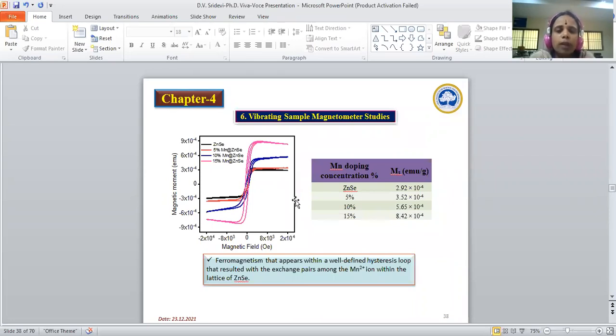This slide shows the vibrating sample magnetometer. Pure zinc selenide nanoparticles show weak ferromagnetic behavior, and the saturation magnetization value was found to be 2.92 into 10 power of -4 when the manganese ion is incorporated into the zinc selenide nanoparticles. The MS loops increase, so the saturation magnetization values increase. As a result, ferromagnetism appears with a well-defined hysteresis loop, resulting from the exchange pairs among the Mn2+ ions within the lattice of zinc selenide.